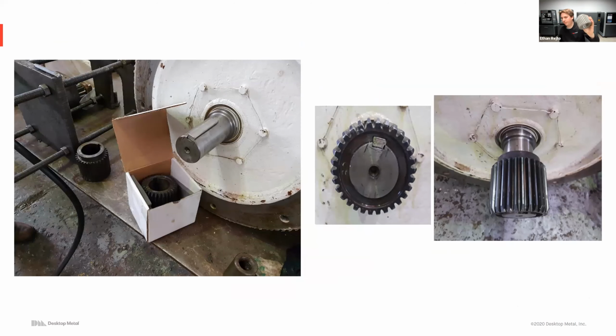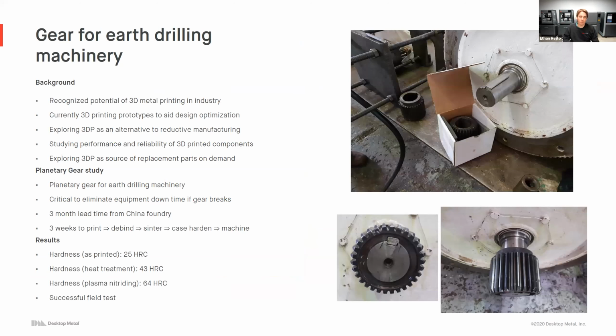Unfortunately, with their original part, they were casting it in a foundry in China. When they had one of these parts break, they found they had a 3-month lead time to get this part replaced from the Chinese foundry. Of course, they did not want to have their drill down for 3 months, so they were looking for an alternative. How do we get this drill back up and running as fast as possible? By switching over to the studio system, they were able to print this part in just 3 weeks.